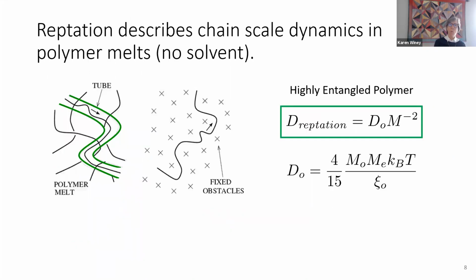So if we just go back to what we know, certainly polymer diffusion is well described by the reptation model. It's this idea that the polymer is constrained laterally. The polymer here can't move left or right on either side of this green tube as easily as it can wiggle forward. The tube is defined by the other entanglements within the system, and so the polymer kind of has to wiggle its way out of the tube.